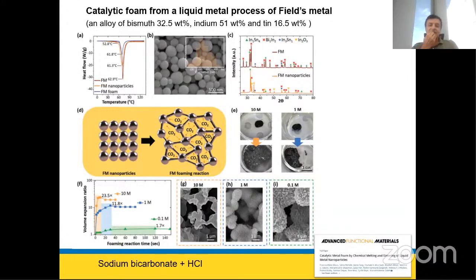And very interestingly, we mixed everything in sodium bicarbonate, as you know, is used for making bread or cooking cakes, baking cakes. So we put everything in acid. Acid interacts with sodium bicarbonate, produces CO2, CO2 very quickly forms this structure. But at the same time, it increases the temperature as well. It melts and the corners of these droplets stick to each other. So we have a very interesting foam. At the same time, we have the formation of functional metal oxide on the surface.